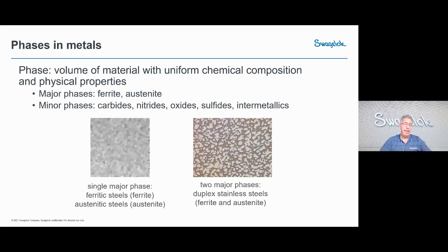On the left-hand side is again a representation of a material with a single phase, and what you see there are, at a higher or lower magnification, the grains which I just went through and showed you on the previous page. These phases, these constituents, and multiple phases also introduce interfaces like grain boundaries, which could be sites for chemical attack. In many cases, chemical resistance or corrosion resistance can be linked back to whether the material is single phase or multiple phase. These can be sources of preferential attack and poor corrosion resistance. So all of this is considered when selecting the proper materials.